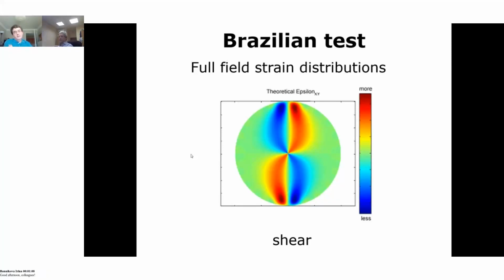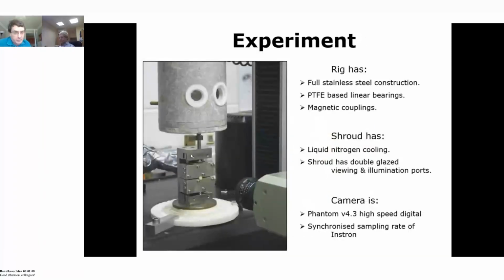So we did an experiment, and this shows the actual setup. Here's the camera. Here is the sample. Here is the support around it. So it's a very large loading structure. And this shroud had liquid nitrogen cooling in it, and we had this insulated little tub here, which I hope is fairly clear. And we had a camera to do the high-speed photography.